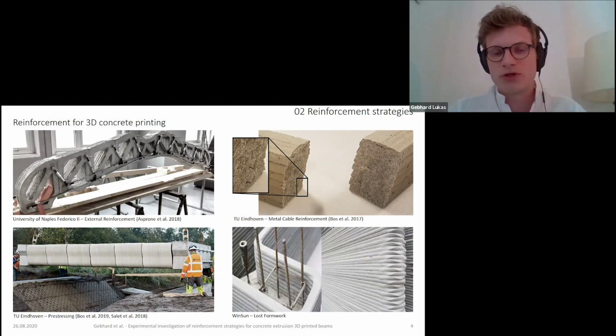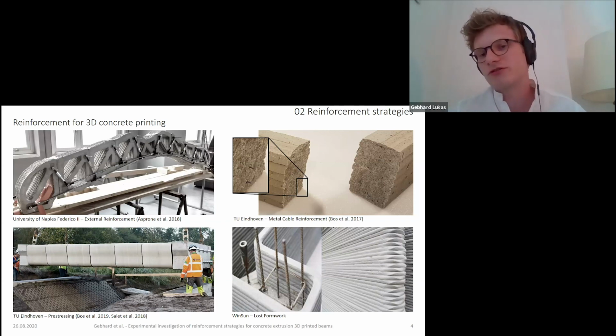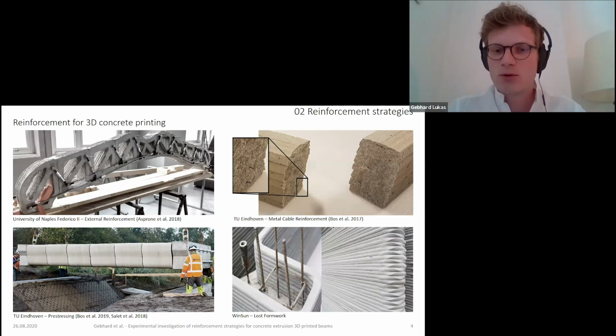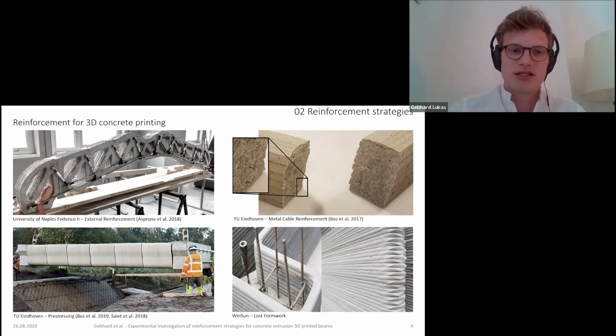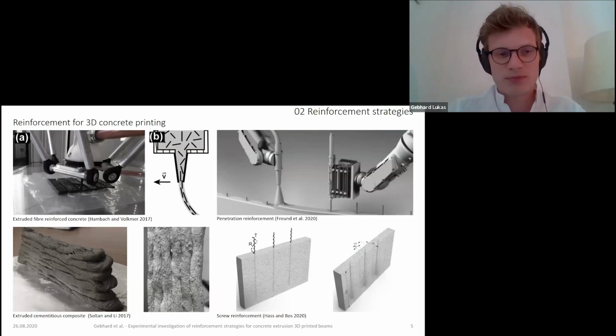Also at TU Eindhoven, the pre-stressing of a bicycle bridge to keep it in compression, and the use of the concrete only as lost formwork, which is already done in industry, where the reinforcement is placed afterwards and conventional concrete is cast around it. Also, there have been some developments in the field of fiber reinforced extrusion. So, for example, on top you see a small sample extrusion for fiber reinforced concrete, and on the bottom, development of strain hardening cementitious composite with fiber reinforcement, also extruded.